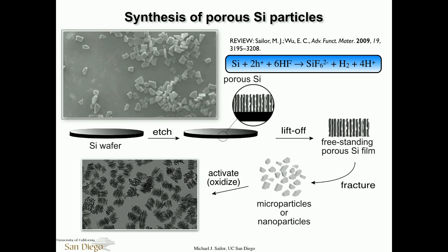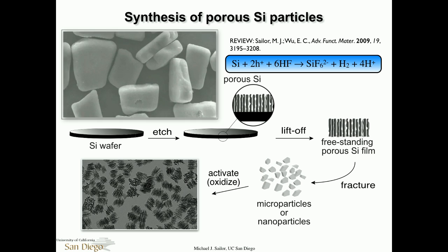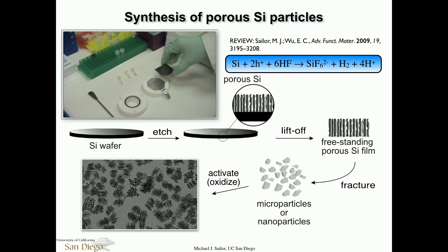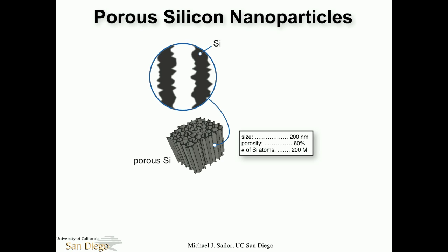These structures are particulate by appearance, but deep inside they're quite open and highly porous. In summary: it's a silicon-based nanoparticle, about 200 nanometers on average — small enough to circulate through the bloodstream — with about 60% porosity. We calculated that a particle of that size and porosity contains about 200 million silicon atoms total. It's a fairly finite, fairly small number.